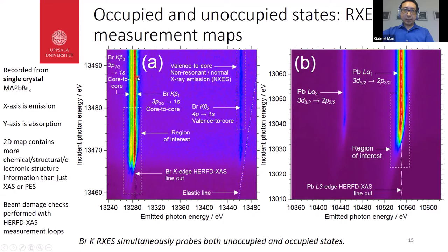So later on in this work, I'll show you some HERFD-XAS, high energy resolution fluorescence detected X-ray absorption spectra. And this is represented by the vertical line cut over here. The region of interest is shown over here in the box. So these are the near edge features. So as a two-dimensional map, there's more information contained here than just X-ray absorption spectroscopy or photoelectron spectroscopy. And typically, these maps are plotted with the excitation energy or the incident photon energy on the x-axis. But I've chosen to plot it this way to show a comparison between this and photoelectron spectra later.